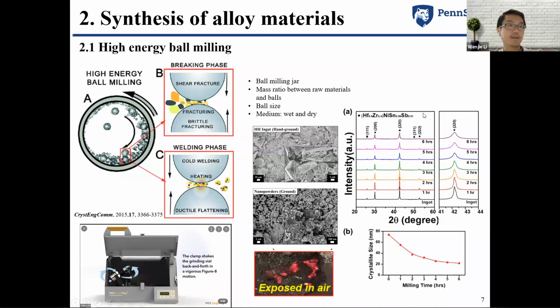And this XRD figure shows how the diffraction pattern changes with increasing ball milling time. As you can see, the diffraction peak is getting broader and broader, which indicates the particle size of the nanopowders is decreasing with increasing ball milling time, from about 100 nanometers to about 20 nanometers.